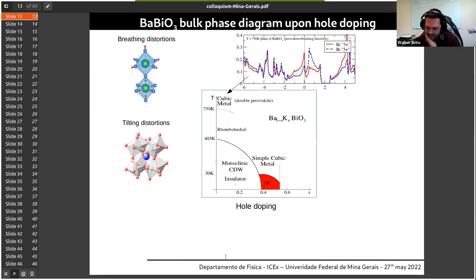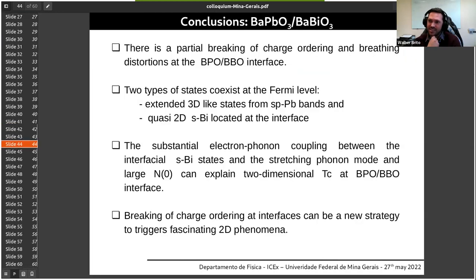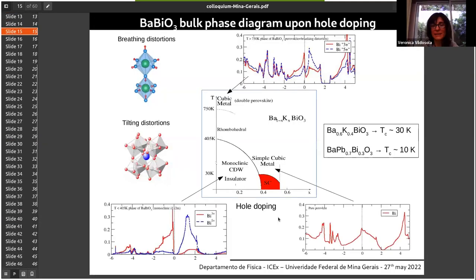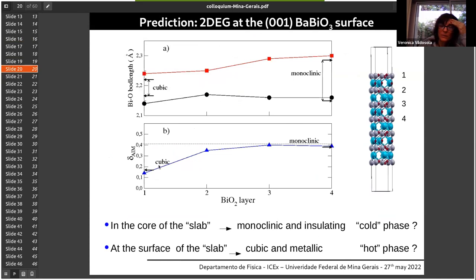Now a technical question. How do you calculate the charge disproportionation? You have the integral of the projected density of states, or? We calculated it with the Bader charge analysis. Oh, Bader, I see. Yes, Bader charge analysis of the bismuth 3 plus and bismuth 5 plus, and this is the difference: 0.4 for the monoclinic bulk situation, and also further away from the surface, and then it decreases to 0.1 more or less at the surface. I see.